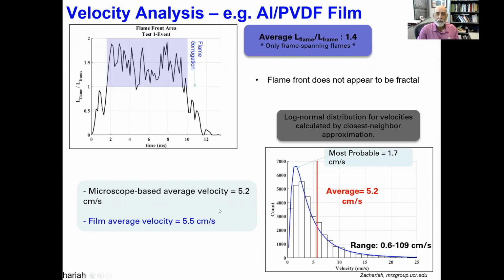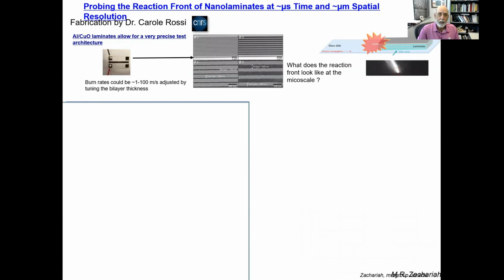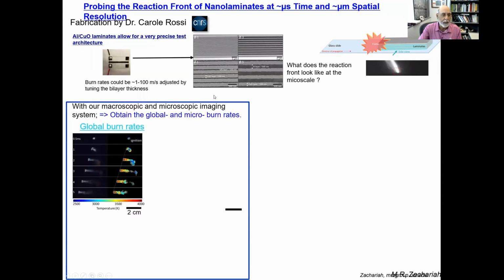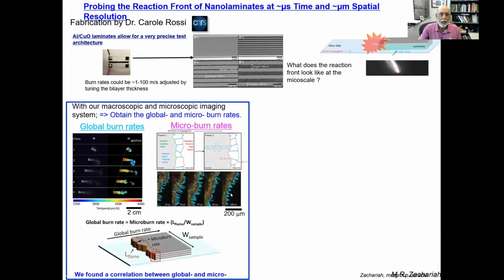Now, to do more controlled studies, we worked with a group in France, Dr. Carol Rossi, and she can make thermite systems which are very well regulated laminar structures of fuel and oxidizer. This is aluminum copper oxide. And so we can look at the burn behavior at the macroscopic level, and then we can look at the burn behavior at the microscopic level in the way I told you. What we're interested in knowing is: is the global burn rate really just the microscopic burn rate times the stretching of the flame? Is the stretching of the flame really what's responsible for an enhanced global burn rate?